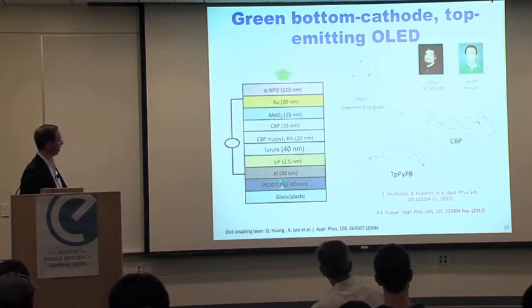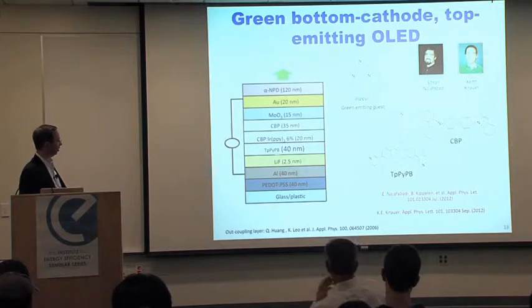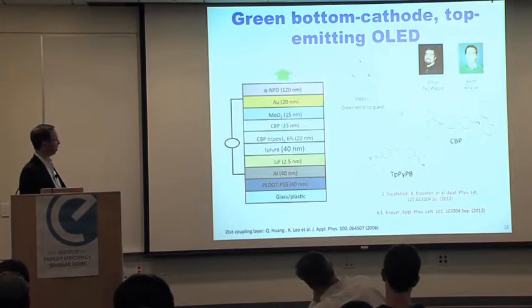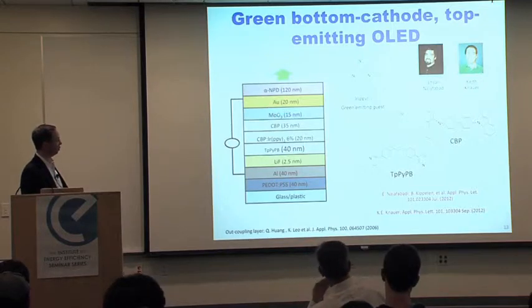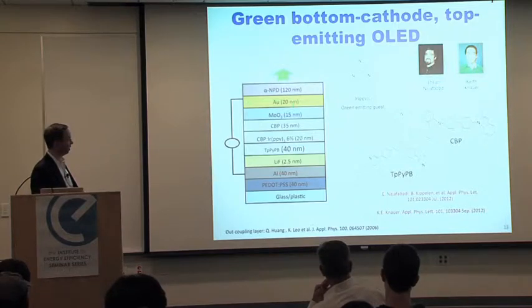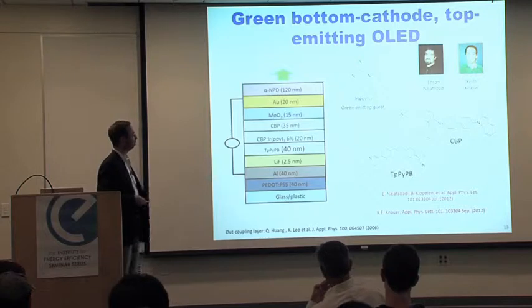But you can see it's a fairly complex stack here where the electron injection is done by that lithium fluoride aluminum cathode, which is now at the bottom. Here we have an electron transport layer. We have that emissive layer. We have a hole transport layer, moly oxide, and a very thin layer of gold is used as the anode. It's on top, and because the gold is sufficiently thin, it's semi-transparent, and the light can go out through the top of the structure.